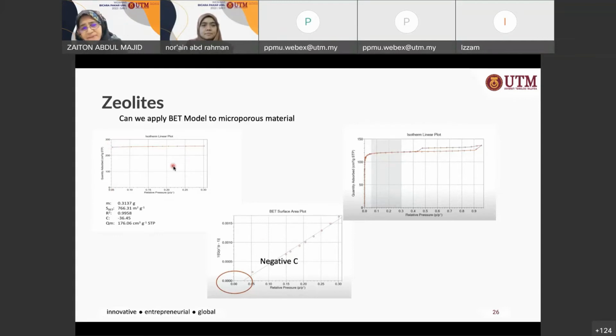And when they run a BET transformation plot for this data from 0.05 to 0.3, they get a negative C, minus 36.45. And this is impossible. Once you have a negative C, you cannot use your data. And the BET surface area of 766.31 is no longer reliable. If you look at the R squared, it is 0.9958. It's not 0.9999, it's 0.9958, right? And the molar volume here, Vm, is 176.06 cubic centimeters per gram at STP. So again, this negative C indicates that the range of data taken here is not applicable.